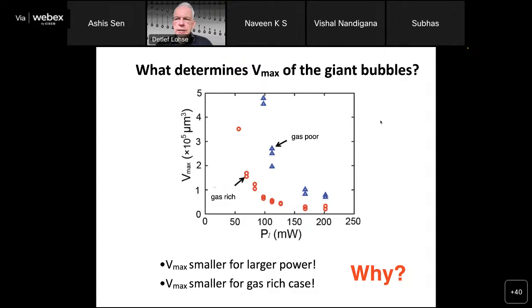And the most remarkable plot of this whole talk, I think, is this plot. This is the size of this giant vapor bubble as a function of the control parameters. I said the control parameters are the laser power on the one hand and the gas content on the other hand. And you get two huge surprises. First of all, when you increase the power of your laser, the size of this vapor bubble goes down. This is just remarkable. You would think more power of the laser, larger bubble. It's not the case. It's a smaller bubble.